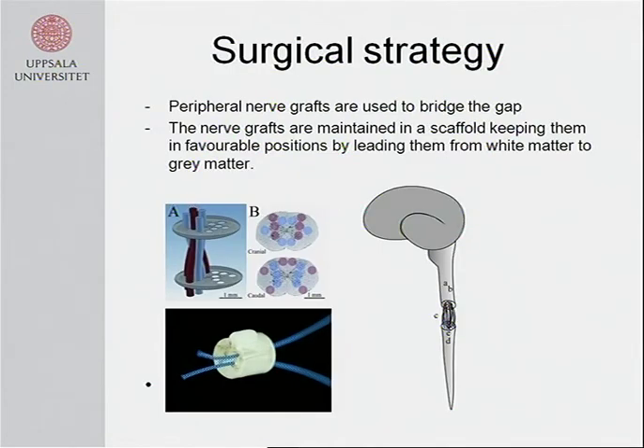So what we have been working on is a nerve graft to bridge the gap of the damaged area. And the strategy is to have a scaffold that could keep the nerve graft in a favorable position, leading them from white to gray matter. This is an image of one of these nerve grafts. And the strategy is then to have a regeneration of the nerves through the damaged zone.